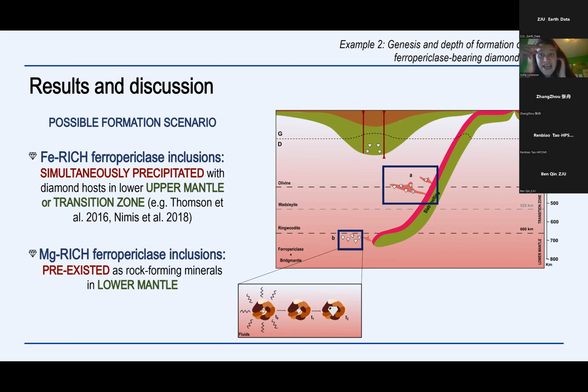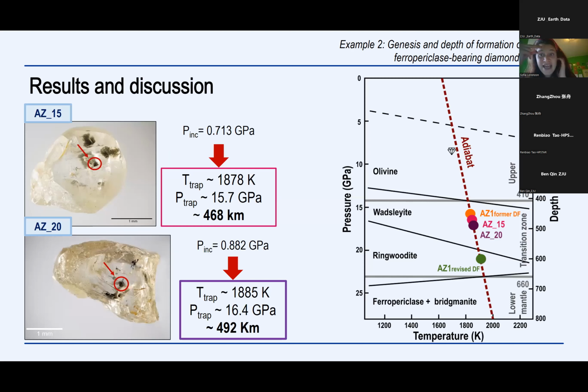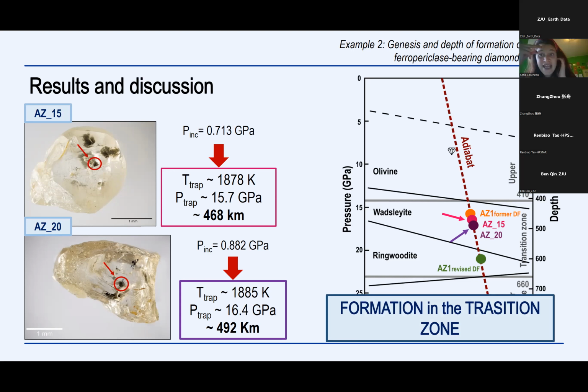So finally, I almost finished. About depth of formation, the results from two different ferropericlase-bearing diamonds tell us that one of these samples formed at a minimum depth of about 468 kilometers, whereas the second one formed at a depth of about 492 kilometers. And these formation depths are extremely similar and correspond to a depth in the transition zone. And this suggests that ferropericlase-bearing diamonds can also form at different and shallower depths with respect to the lower mantle. And this is also supported by the previous data.